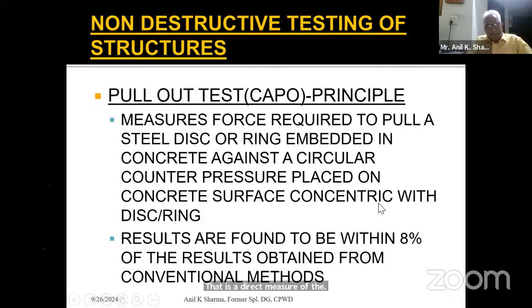So the principle of the pull-out test is that it measures the force required to pull a steel disc or ring embedded in concrete against a counter pressure placed on the concrete surface concentric with the disc. Results are found to be very close, within 8% accuracy of the actual strength of the concrete. The surface at the test location is ground using a planing tool, and an 18.4 mm hole is made. We have detailed out the complete procedure and instrumentation.